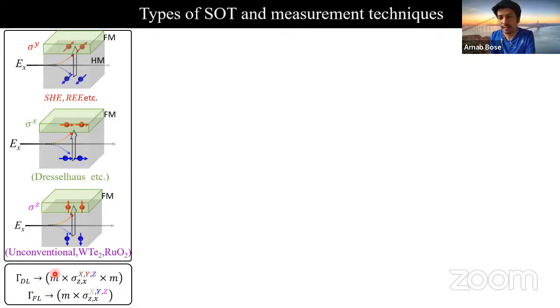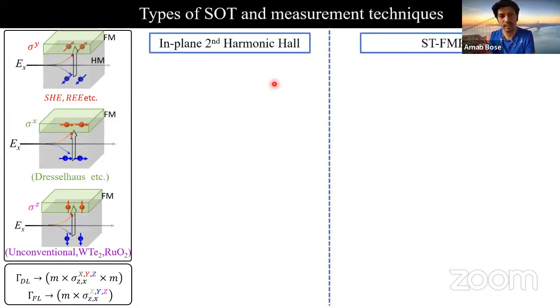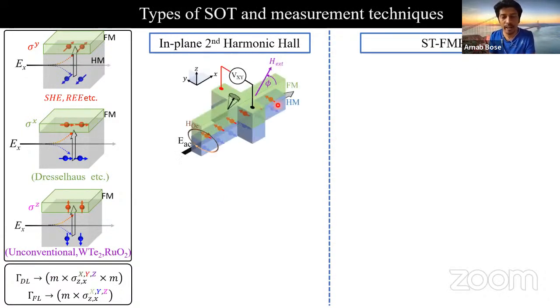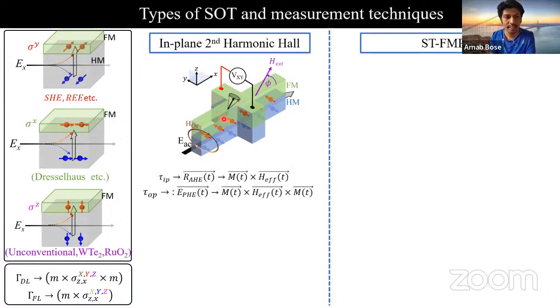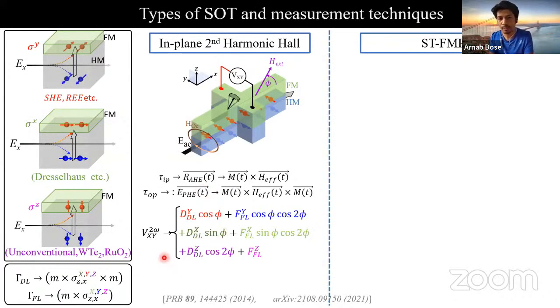To quantify the spin torques experimentally, there are 2 techniques, in-plane second harmonic Hall and spin torque ferromagnetic resonance. In this technique, we have a bilayer consisting of a ferromagnet and the source of spin current. Now we run low frequency current in the system. Because of various current induced torques on the magnet, the magnet oscillates both out of the plane and in the plane, resulting in oscillatory magnetoresistance from anomalous Hall effect and planar Hall effect. Meaning we have alternating current and alternating resistance, and they mix together to produce second harmonic Hall voltage.